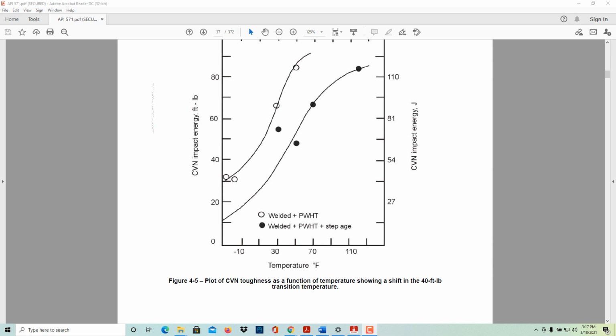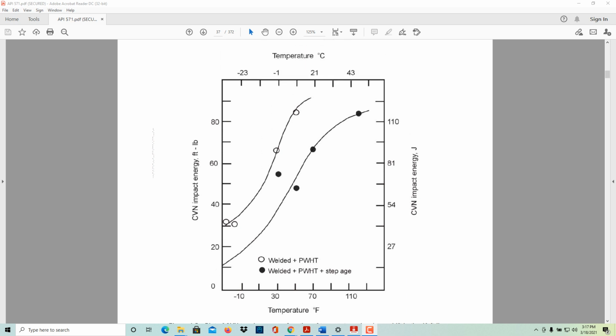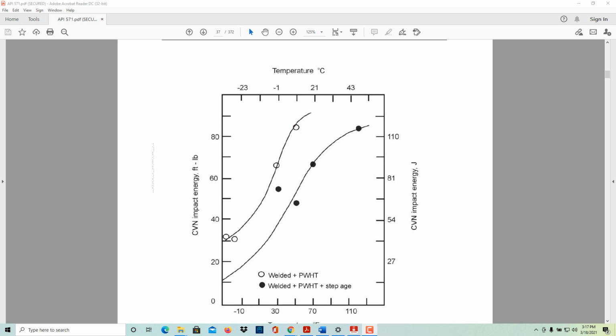Plot of CVN toughness as a function of temperature, showing a shift in the 40 foot-pound transition temperature. Temperature on this axis, CVN impact energy in foot-pounds on this axis. Welded plus post-weld heat treatment. Welded plus post-weld heat treatment plus step age.